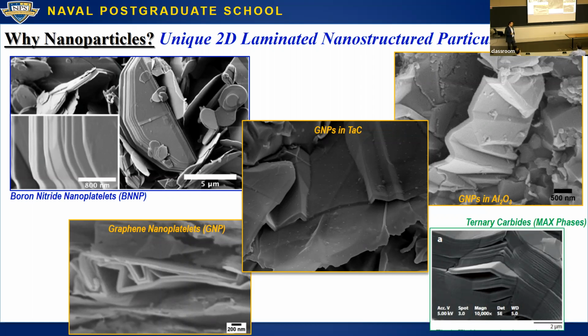If you start going beyond that, you start losing the unique properties that occur at nanoscale and start going more like a piece of graphite, for example. At 100 layers, you're pretty much dealing with graphite. But when you're still at 10 to 20 layer range, you actually get these interesting deformation mechanisms. And you see these graphene platelets. Graphite is not the material we think of as being very ductile, right? Yet you see these platelets, you can see that they're deforming at 90-degree angles without fracturing. It's a very interesting process and property.